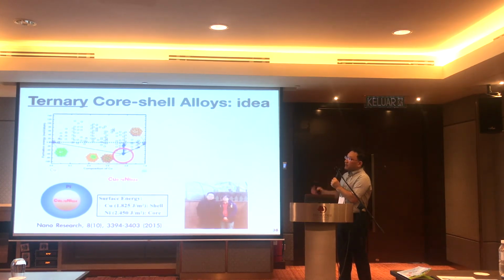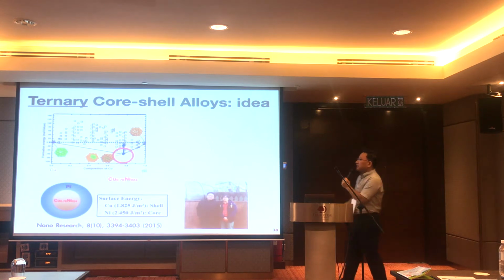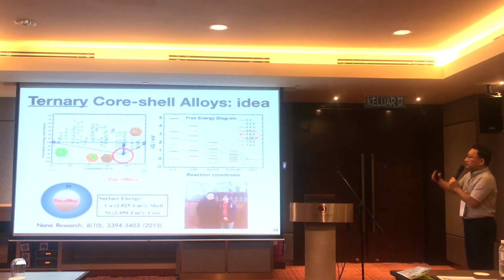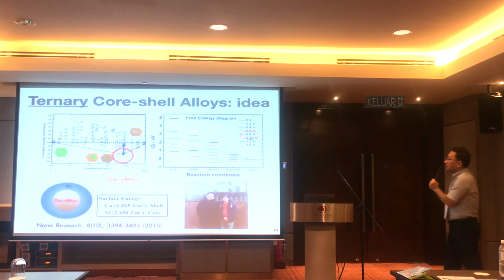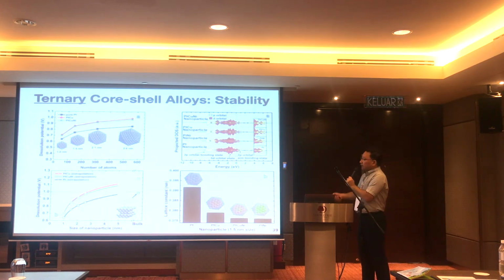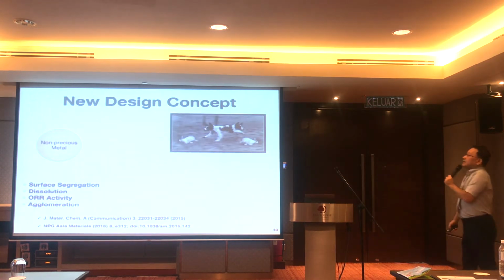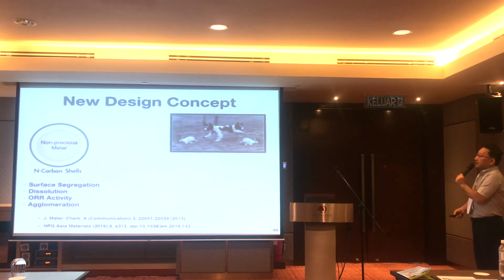Binary compound is not good. Maybe ternary will solve the problems. So by collaborating with the Tokyo Institute of Technology in Japan, we try to find a better ternary compound. What we found is copper and nickel coated by platinum. As far as we know, this is the best material so far. I'm going to propose to synthesize this one if there is any experimentalist. The durability is good, and the activity is also much better than platinum. You need half the size of the platinum to keep the same stability. Okay? But eventually, I'm going to provide the new design concept here.